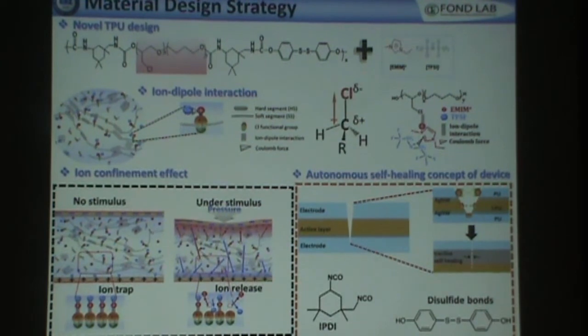So for the ion confinement effect, when there is no stimulus, these ions are trapped by the chlorine functional groups, and then under stimulus such as pressure, the ions are pumped to the electrode-electrolyte interface that increases the EDL capacitance change. So this ion trap and release concept ensures that we have higher sensitivity in our system. For the autonomous self-healing concept here, we have high chain mobility IPDI, as well as dynamic disulfide bonds in the backbone of the TPU. This ensures that we have higher self-healing speed at room temperature.